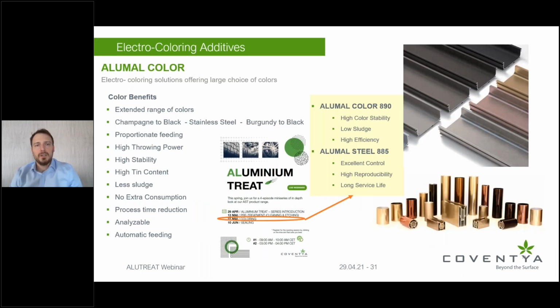Okay, then after anodizing, the option was using electrocoloring additives. And here we have three major groups. The coloring agent based on tin, the coloring agents based on nickel, and then we have two subgroups, the coloring agent based on iron and also based on copper.